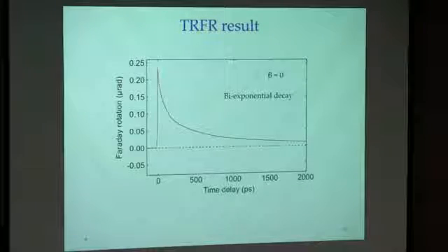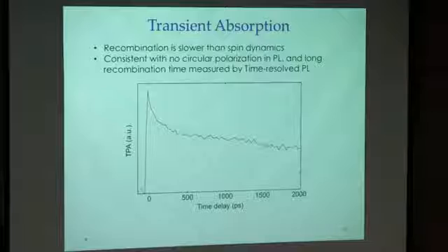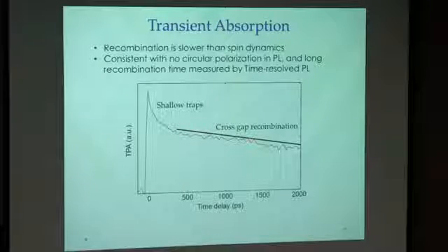So let's first look at the zero field data. It shows a biexponential decay; the shorter time scale is 150 picosecond, and the long one is 1170 picosecond. So what are they? We also look at the transient absorption, where we don't measure the polarization of the light, but just measure the light-induced absorption change in the material. And we also see 2 time scales. This small component has a short lifetime, also 150 picosecond. And this is a much longer time scale component, which we consider to be the cross-gap recombination or the exciton recombination. This lifetime is much longer than 2 nanosecond, or 2,000 picosecond.